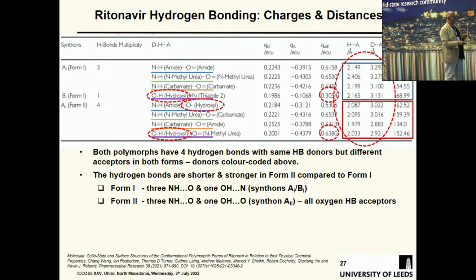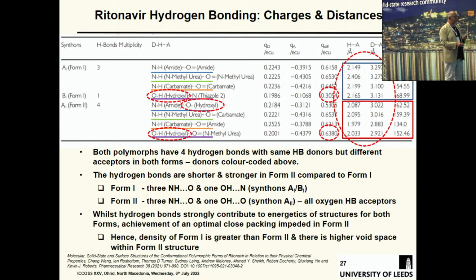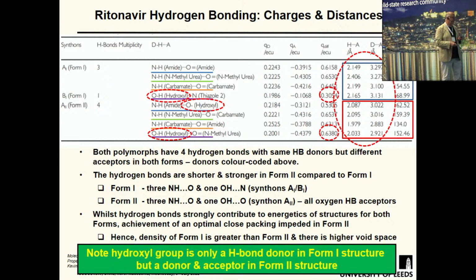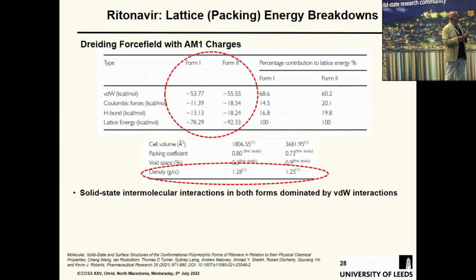In Form 1, there are these 3 NH...O and 1 OH...N synthons. In Form 2, there are 3 NH...O and 1 OH...O. Because of the conformations, they're able to get closer. Because they get closer, they get stronger. Whilst the hydrogen bonds strongly contribute to the energetics of the structures for both forms, achievement of an optimal close packing is impeded for Form 2. In order to make those hydrogen bonds, it can't close pack, and it doesn't. So what comes out of that is that the hydroxyl group is only a hydrogen bond donor in Form 1, but a donor and acceptor in Form 2.